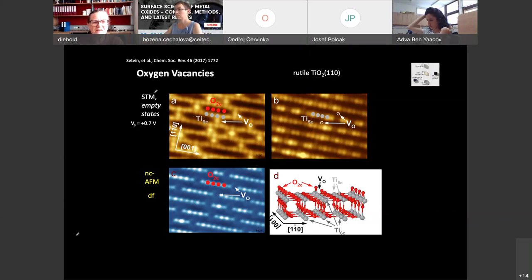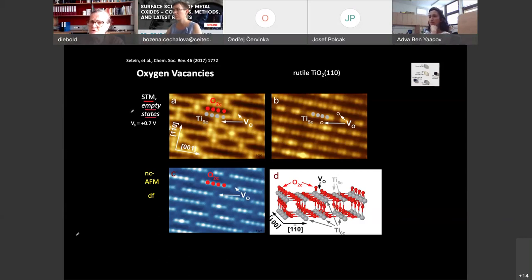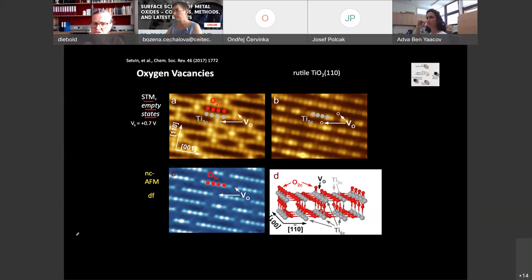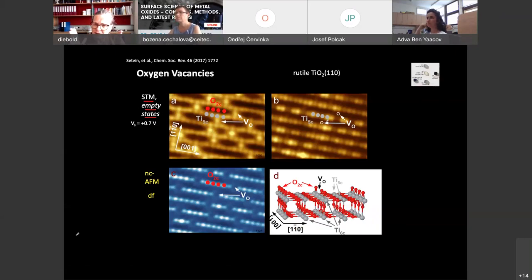We started talking in detail about what we see. You see oxygen atoms and then a hole — a vacancy — and then probably the nice question: what happens here? There are some relaxations; some of the oxygens move down a little bit when you make this oxygen vacancy, so the neighbors change their lateral position slightly. This is scanning tunneling microscopy imaging the empty states in constant current mode — that's used in 99% of papers out there in the literature about metal oxides.